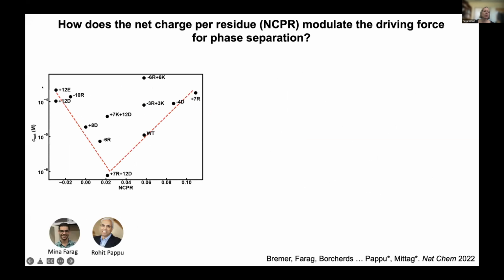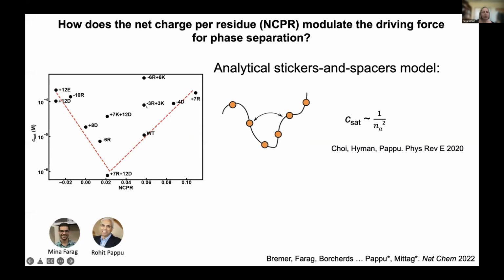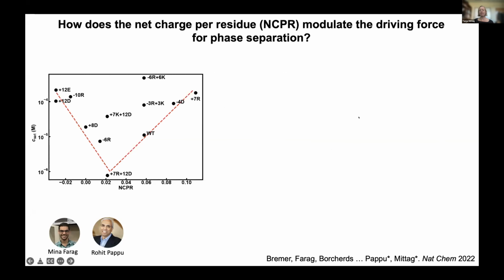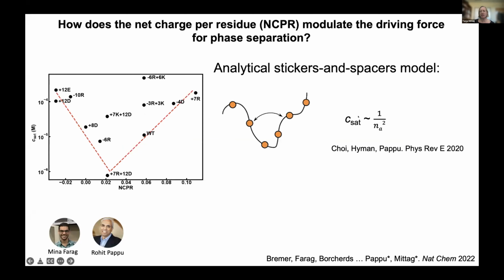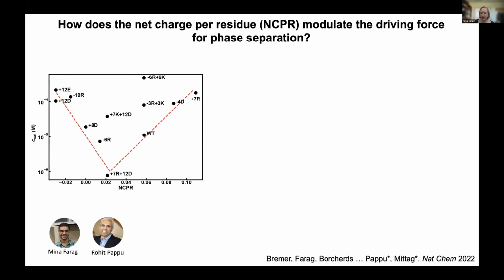And of course, we had this set of sequences where we only changed charged residues and didn't touch the aromatic residues, right? And when we plotted their saturation concentrations against the net charge per residue, well, we saw something that didn't really resemble this kind of V-shaped plot. So either this premise was wrong, or perhaps there was something additional going on. And these outliers would tell us that perhaps we missed some stickers or some other effects in the sequences. So we made use of the analytical form of the stickers and spacers model that Rohit already introduced, where we can estimate the saturation concentration from the number of stickers in the sequence. And there's a square here because, of course, you need 2 stickers to make a networking interaction.